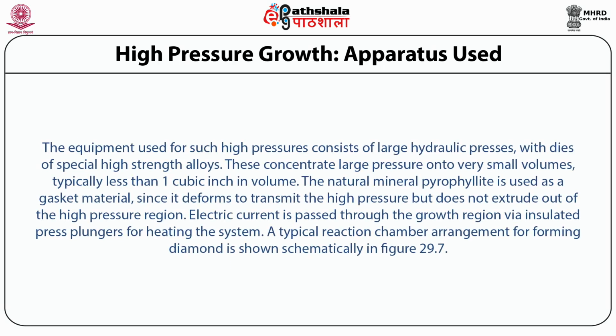Now let us see what is the apparatus used. The equipment used for such high pressures consists of large hydraulic presses with dies of special high-strength alloys. These concentrate large pressure onto very small volumes, typically less than 1 cubic inch in volume. The natural mineral pyrophyllite is used as a gasket material since it deforms to transmit the high pressure but does not extrude out of the high pressure region.